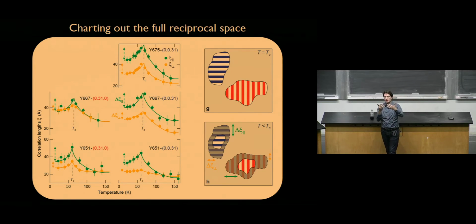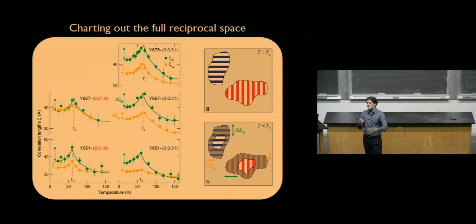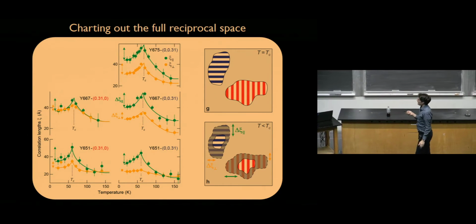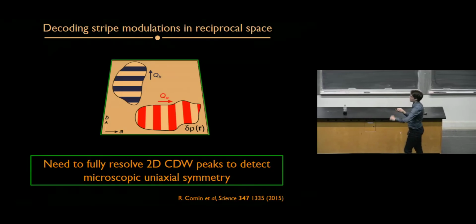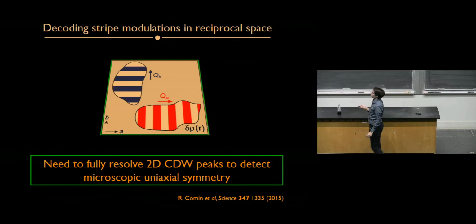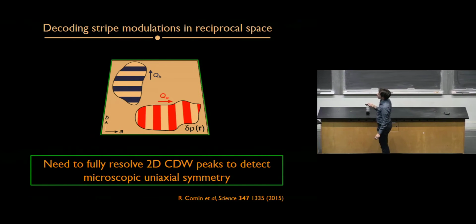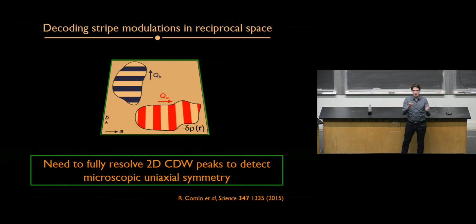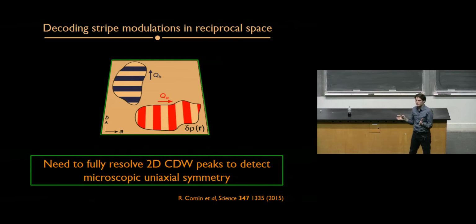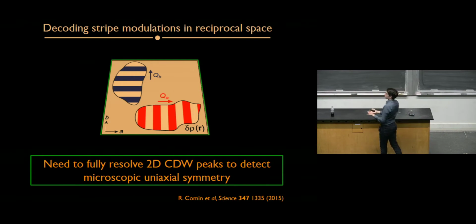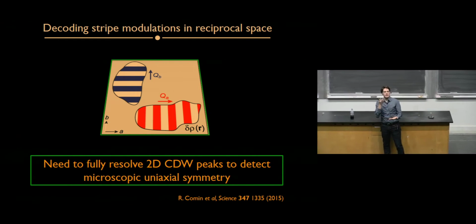Your charge order state is broken into domains that are locally unidirectional. And we studied this as a function of temperature, but I don't have time to talk about it, so let me skip it. Yes, so by resolving the two-dimensional peak structure in reciprocal space, we can basically tell that there is a broken symmetry at the local scale, and these domains are really stripy. They're not checkerboard-like, again, locally.